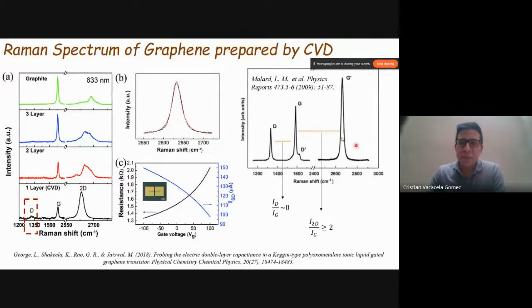For example, in this other work, the authors also report the production of single layer graphene. But if you compare this Raman spectrum for this single layer graphene with this one here, we can see there is a D peak, so intense when we compare it. In both works they use chemical vapor deposition to prepare the samples. But the idea is to highlight how very simple parameters, just changing one, for example, can change your graphene samples dramatically.